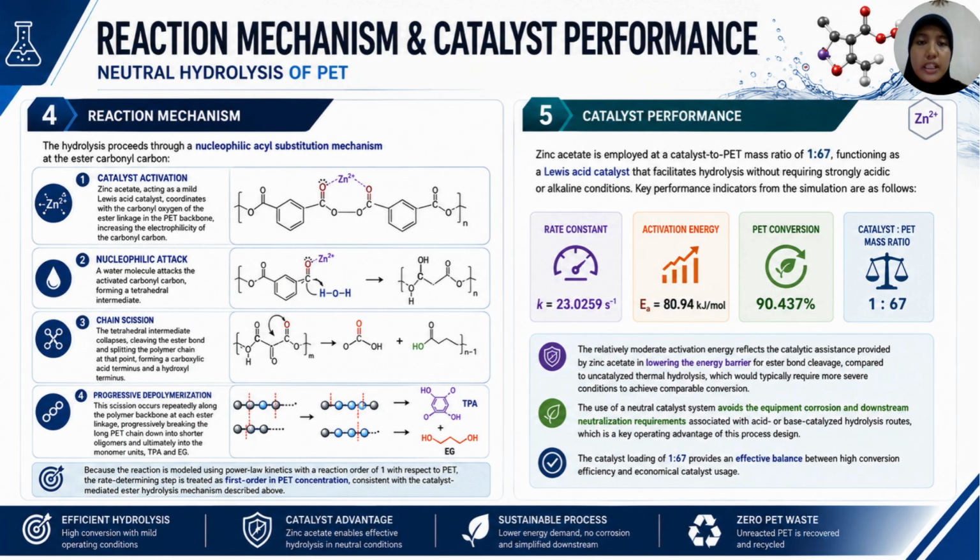Now let's look at the reaction mechanism and catalyst performance. The hydrolysis follows a nucleophilic acyl substitution mechanism at the ester carbonyl carbon, consisting of 4 core steps. First is the catalyst activation. Zinc acetate acts as a mild Lewis acid, coordinating with the carbonyl oxygen to increase the electrophilicity of the carbonyl carbon. Second is the nucleophilic attack.